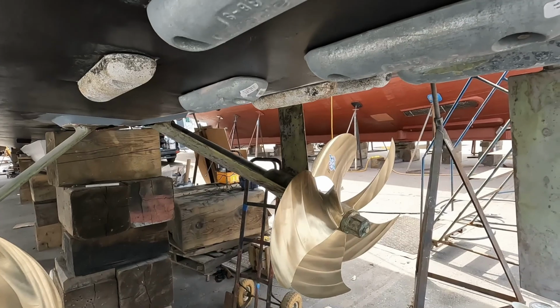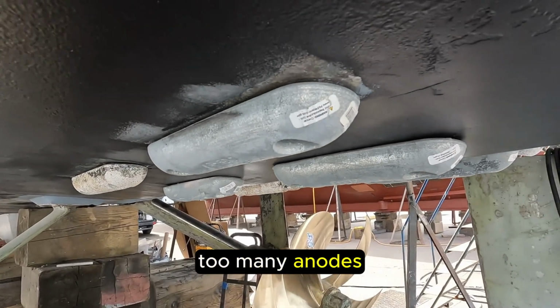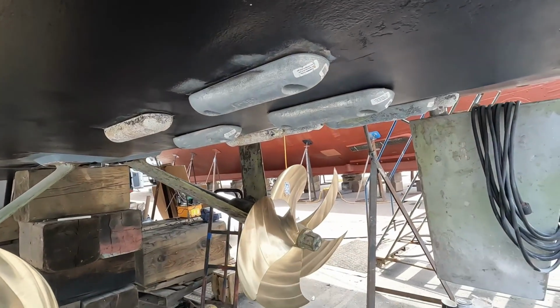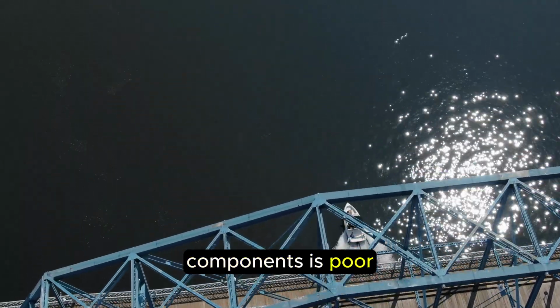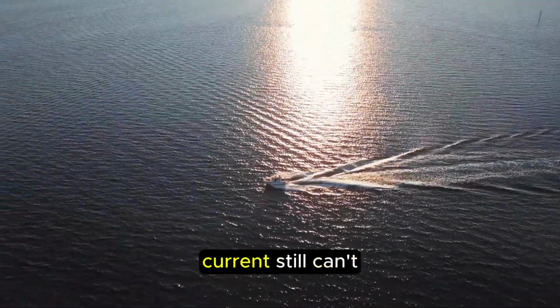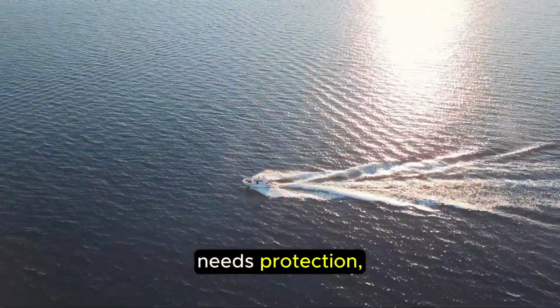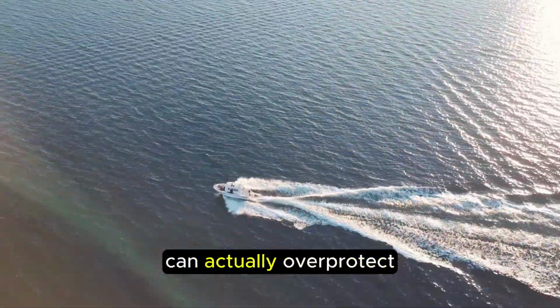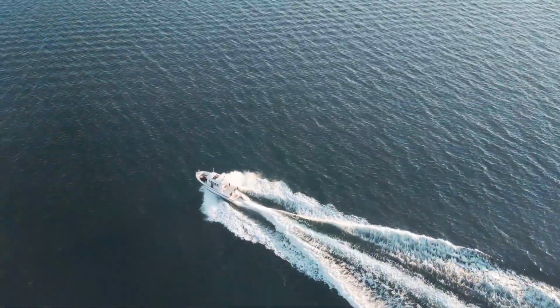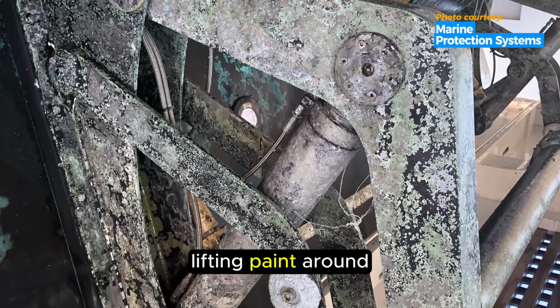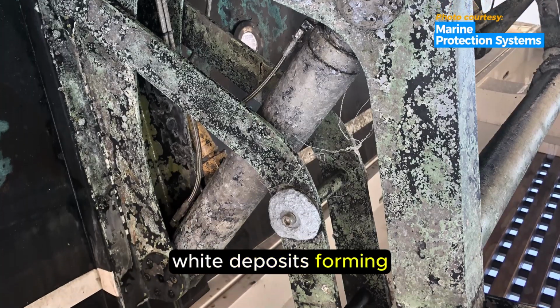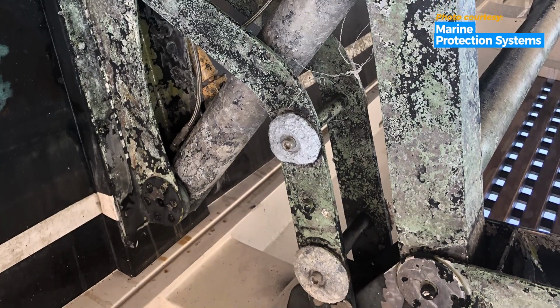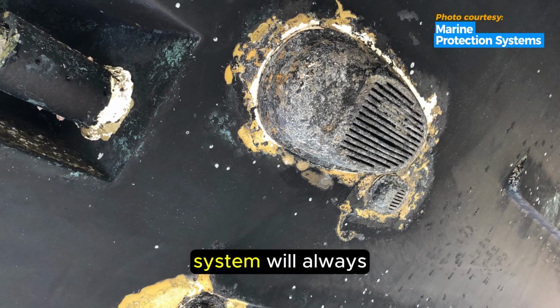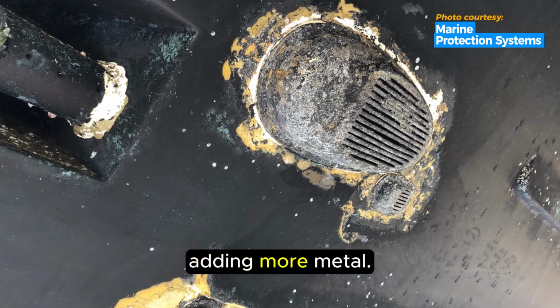Do more anodes mean more protection? Not necessarily. In fact, too many anodes can create problems of their own. If bonding between components is poor, adding more anodes doesn't help because the protective current still can't reach the metal that needs protection, and oversized systems can actually overprotect the boat. Signs of overprotection include lifting paint around metal fittings and hard white deposits forming on propellers or shafts. A properly sized, properly connected system will always perform better than simply adding more metal.